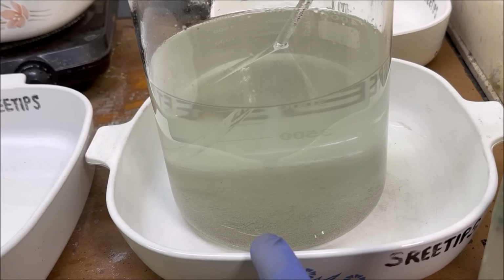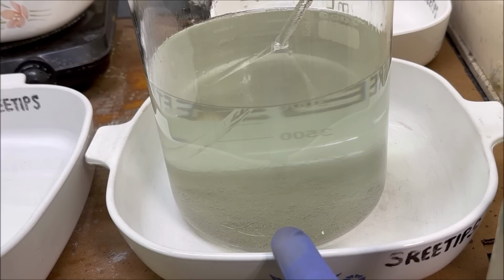And the reason that's important is because we do not want a high level of free nitric acid in our electrolyte. In the impure silver that we're going to be feeding into the anode basket, we may have some palladium. Palladium is soluble in nitric acid. So if we've got a whole bunch of free nitric in our electrolyte, then it will tend to dissolve the palladium in the anode basket, and then that palladium will leach down into the silver cell.